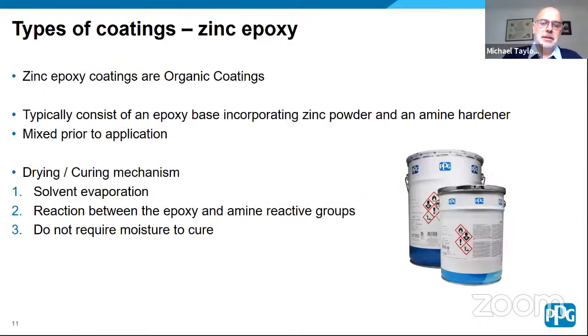So the other type of zinc primers that are typically used would be the zinc epoxies. The zinc epoxies differ from the zinc silicates in that they're an organic coating, and they typically consist of a two-part product. So you've got your base component into which the zinc powder is mixed, and then an amine is usually used as a hardener. The two are mixed together prior to application. The curing mechanism for that again is solvent evaporation and then reaction between the epoxy and amine reactive groups to give a cross-linked film. And in this case, they don't require moisture to cure.